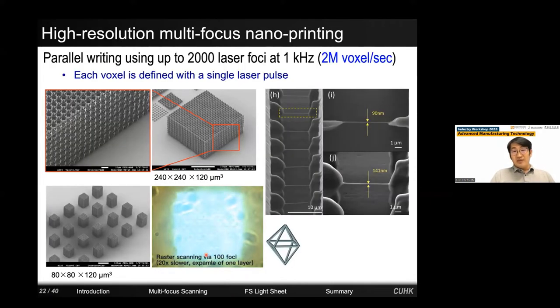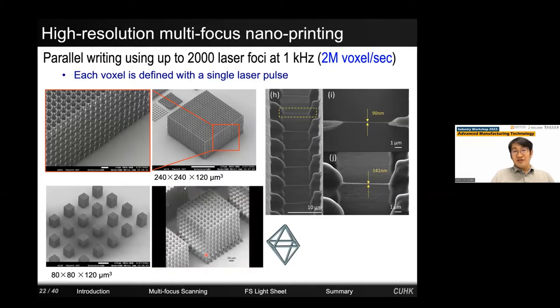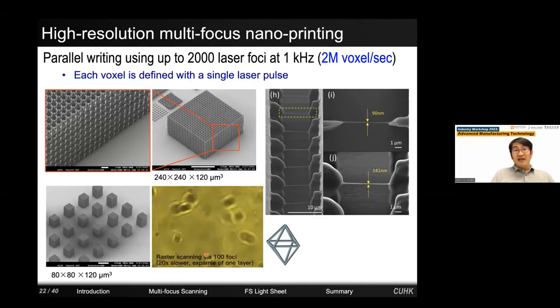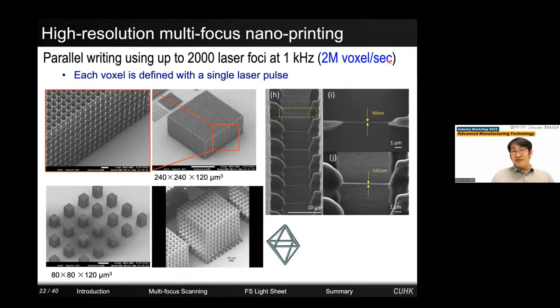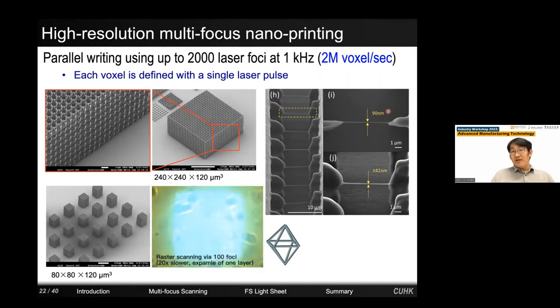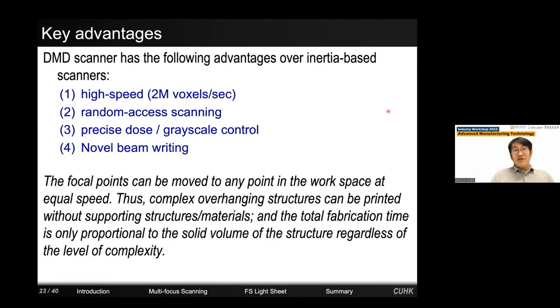In the recent one or two years, we further enhanced the performance of the system by using a regenerative laser amplifier. And nowadays we can use up to 2000 laser foci, achieving a 2 million voxel per second writing speed and breaking the record of resolution down to 90 nanometers. So to quickly summarize, we use a digital micromirror device to perform high-speed multi-focus scanning, and each focus is individually programmable and can perform random access scanning. In fact, each focus can also carry different laser powers, so they achieve grayscale control. Very capable system to create three-dimensional structures.